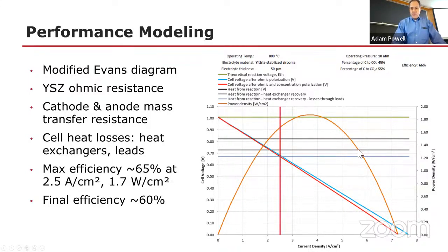This orange curve is the power density, and so you can see that we have a number of different heat losses, and the maximum efficiency that we can get out of this while staying in thermal balance, so that we don't just lose power and the cell cools down and freezes, is about 65%, with the final efficiency around 60%. This is around twice the efficiency of the integrated gasification designs, whether with combined cycle or a fuel cell. So quite a bit more efficient.